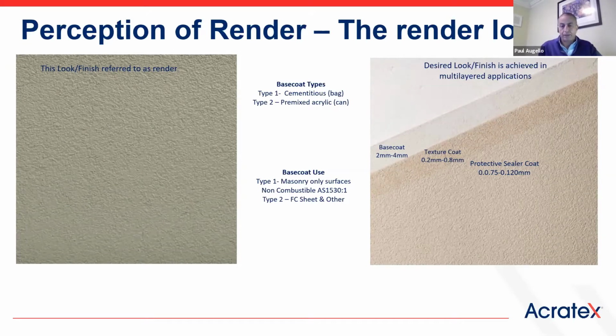And that's the critical part to this path here, is that to achieve that look that everyone perceives as a render, it's generally about a three-layer system. A being the base coat, that's generally the levels off the surface, which can be 2 to 4, 6 mil, depending on what surface you're putting it over. You've got the texture coat, which is under 1 millimeter thick, and that's really what gives you the aesthetic look, which everyone refers to as this render look, because that's the part that actually looks like render. And then you've got a protective layer coat for weatherproofing purposes and keeping the surface clean and maintenance free that sits over the top of that.